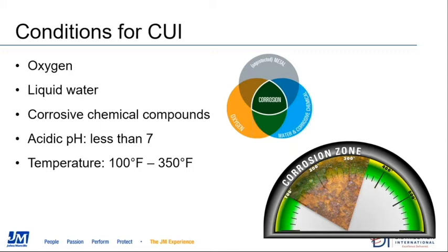You need the presence of some type of a corrosive chemical compound. Typically, this would be some type of a corrosive salt introduced into the system from the environment or possibly from the insulation. You would need an acidic pH, something under 7, and then you need a temperature that is considered to be the corrosion zone for temperature, typically agreed by most folks in the industry to be 100 degrees to 350 degrees Fahrenheit. And we'll talk a little bit more about that shortly.